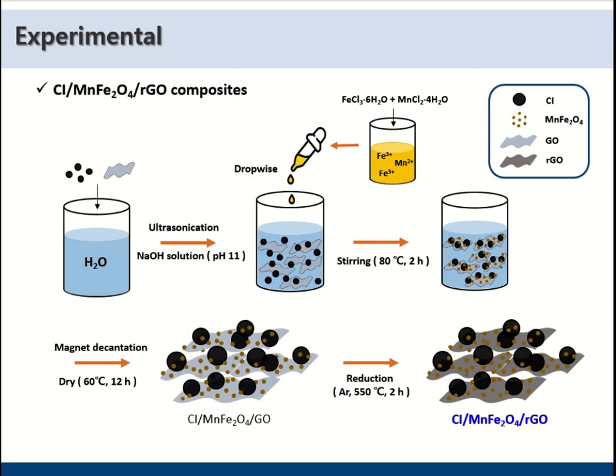This is the experimental method of CI/MnFe2O4/rGO. We dispersed CI and GO in distilled water and added FeCl3 and MnCl2 aqueous solution dropwise.